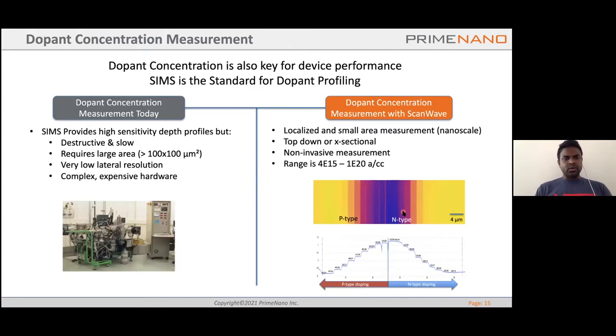The next application I want to talk about is the dopant concentration measurement. While there are other electrical AFM techniques which you use for dopant concentration, traditionally the industrial standard is using secondary ion mass spectroscopy, SIMS. But the problem with SIMS is that this is a destructive technique as you are sputtering off the material, and it is relatively slow, requires large area for characterization. That makes the spatial resolution really lower. Again, the complexity and the cost which comes with this is also a bit higher.